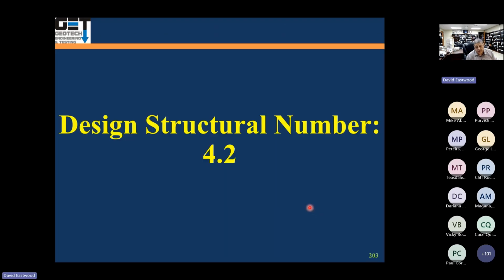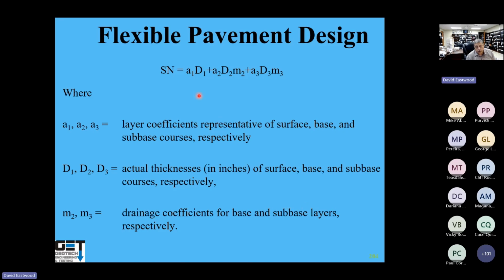So for a design structural number of 4.2, we go to the AASHTO pavement design equation. Your structural number is 4.2 = A1D1 + A2D2 + A3D3. This corresponds to the structural number for the material that we're using times the depth. This is the asphalt surface, which is 0.44 times the depth. This is the structural number for the base times the thickness of the base. Structural number for the stabilized subgrade times the thickness. A1, A2, A3 are layer coefficients. D1, D2, D3 are the actual thicknesses.